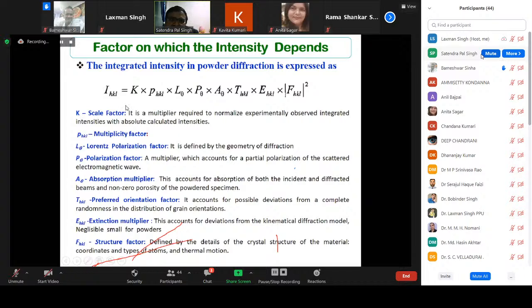This is called the scale factor. P HKL is called the multiplicity factor. This is the Lorentz factor, and this is the polarization factor. There is an absorption multiplier, there is preferred orientation, there is also an extinction multiplier, and this is the structure factor. This is the most important factor, which defines the crystal structure of the material, including the atom types, coordinates, and thermal motions. The intensity is proportional to the square of this structure factor.